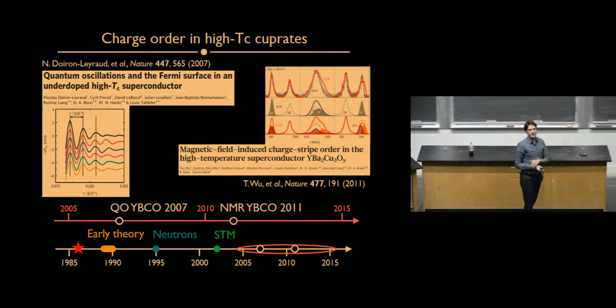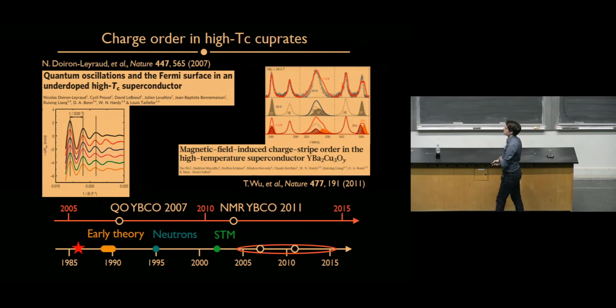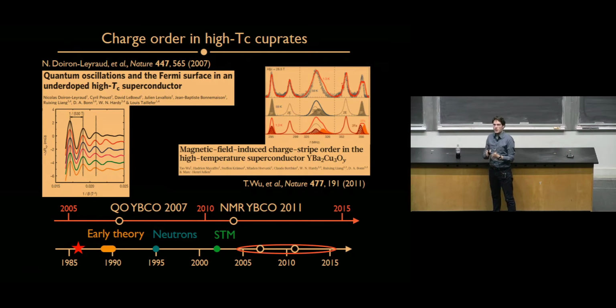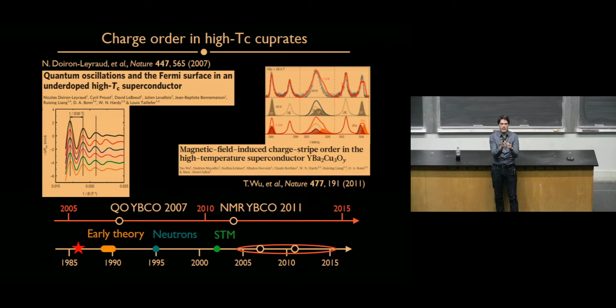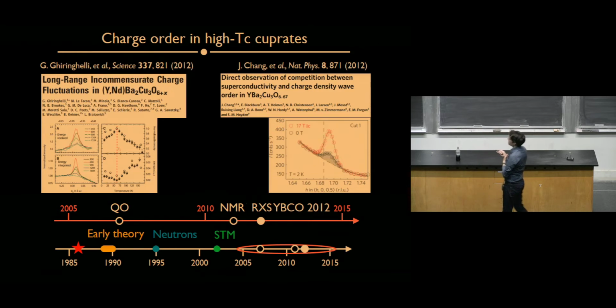This is a very fancy technique that uses high magnetic fields to cause oscillations in the transport properties, from which you can indirectly detect the presence of electronic orders. I don't want to bore you on that, so I'll not touch on that. But more recently, it was shown using NMR that there are inequivalent sites in your copper-oxygen planes at high magnetic fields. If there are inequivalent sites that should be equivalent, which you can see through the presence of different nuclear transition lines, the only way that can happen is if you have a charge order that distinguishes the electronic states at different copper or oxygen sites.